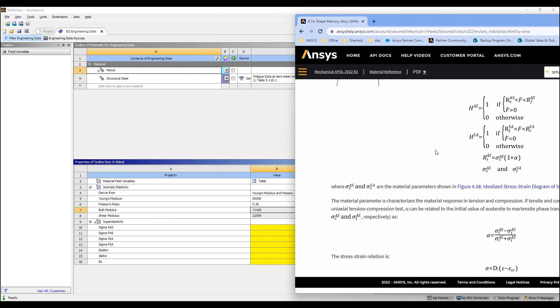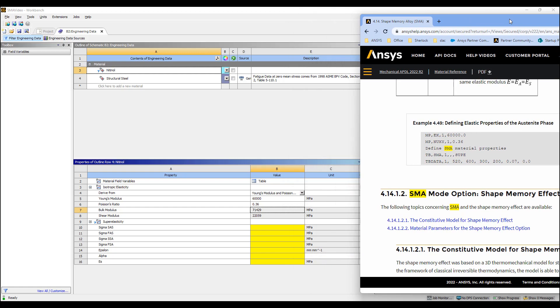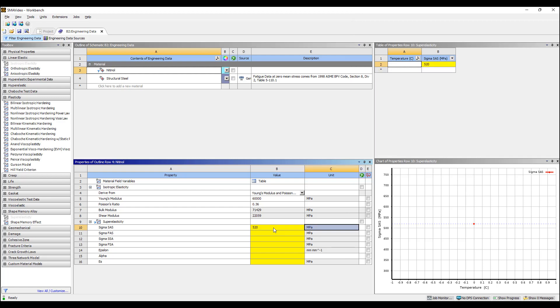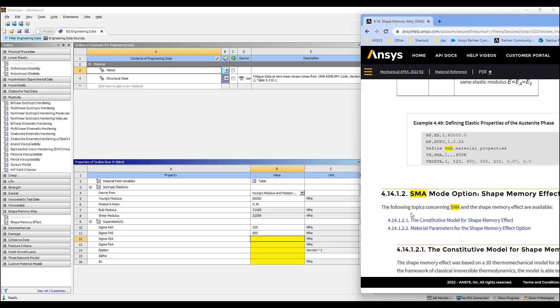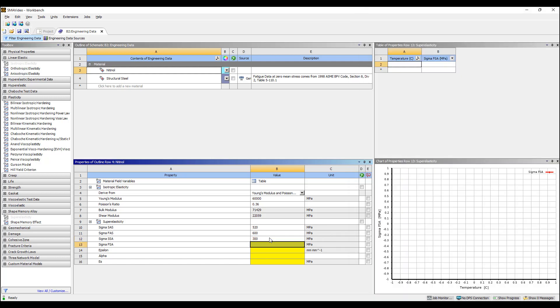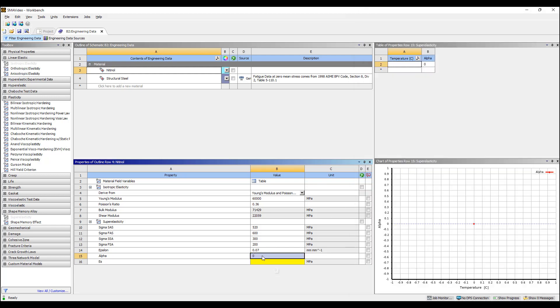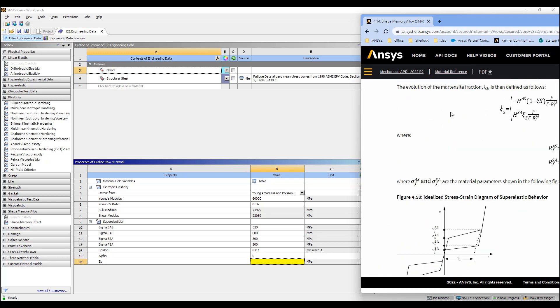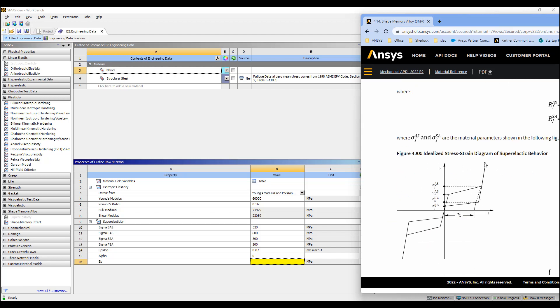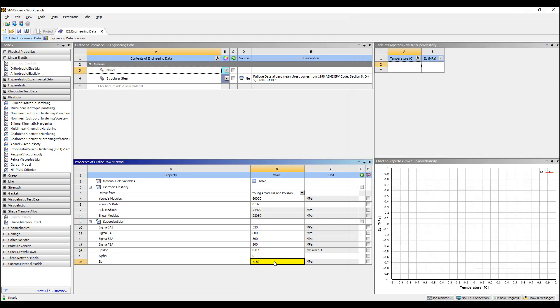This is the information we can put in and we have an example material here from ANSYS. So we're going to start at 520 MPa and go to 600, then on the downward slope go from 300 down to 200. The maximum transformation strain is 7%, and this value controls the difference between compression and tension — the ratio of tension versus compression. Finally, this last value is the elastic modulus of the martensite phase. This slope doesn't have to equal the austenite slope. I'm going to make them the same for now: 60,000 MPa.